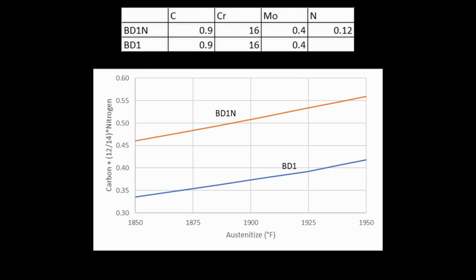And then I've got a chart showing BD1 carbon in solution versus temperature, and BD1N carbon plus nitrogen in solution. We actually multiply by 12 divided by 14, because those are the ratio of the atomic weights of the elements. So for BD1N with the nitrogen, you have to add a little bit more nitrogen than you would carbon, just because it's a little bit heavier element.